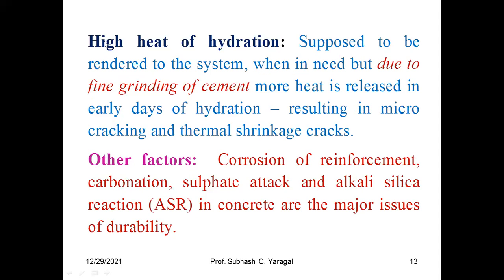We have problem with high heat of hydration. It is supposed to be delivered to the system when in need; we require heat of hydration whenever it is needed. But due to, again, fine grinding of cement, that is the advanced technology for grinding, more heat is released in the early days of hydration. That results in micro cracking and thermal shrinkage cracks. Okay. This also is one thing which has to be duly taken care of so as to increase the durability of concrete.